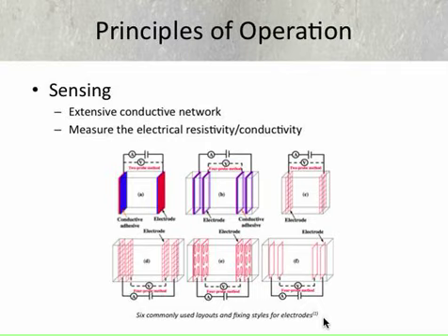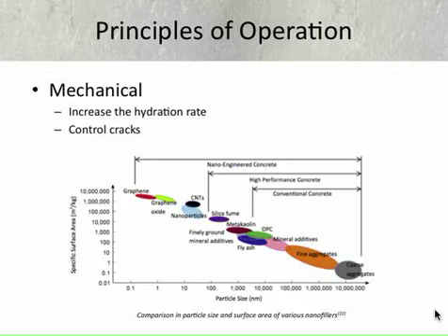This figure here shows 6 commonly used systems from a review paper, and there was a 4-probe method that was found to be the most recommended using a DC power supply, but also a 2-probe method, equally usable. Some other problems were presented with respect to fixing the electrodes on some material where some preferred to embed it, while others wanted to adhere it. And ultimately, however, the data is recorded using an instrument and then it can be analyzed.